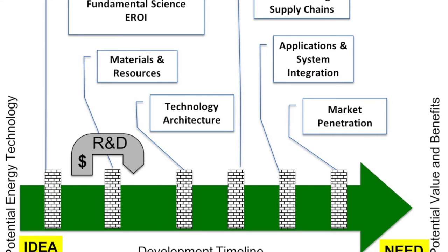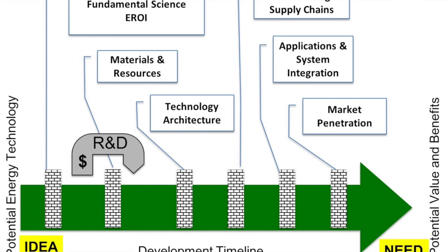We'll have to do some more R&D to try and get intermittent electrolyzers that can survive. Which is an ongoing R&D problem. I've had discussions with scientists working at the CNRS in France, and that's how they get a lot of funding. Figure out how to extend the durability of the fuel cells when the current that is feeding them is intermittent. You mean the electrolyzer? Yeah, exactly. So now we're realistically talking about a lifetime of around 20,000 hours. So a little bit more than 2 years functioning.